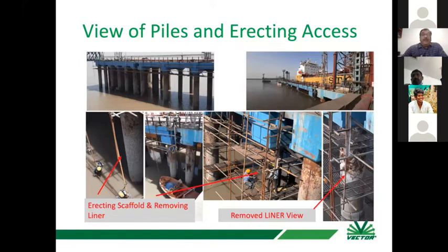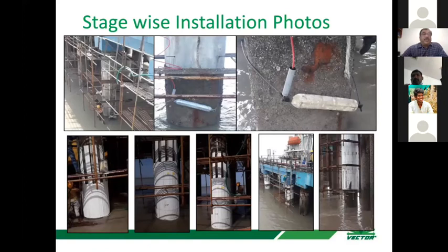And the anodes have been installed on the surface of the column. The first left-hand side photo shows the strip anode with a special fabric over the anode, which will keep the anode, like we want the anode to corrode, zinc to corrode. So by wicking action, this cloth will keep the anode corroding.